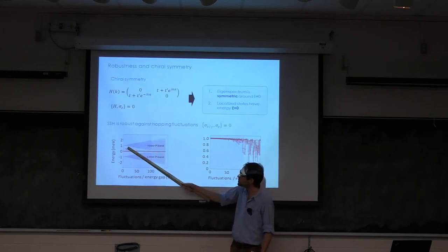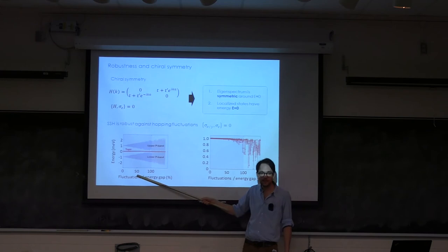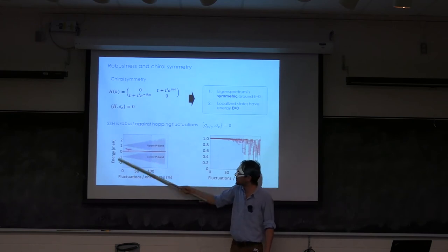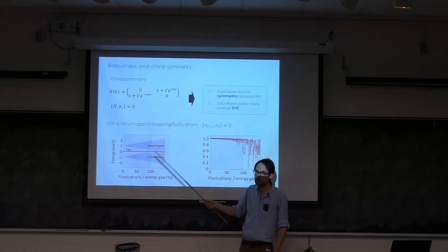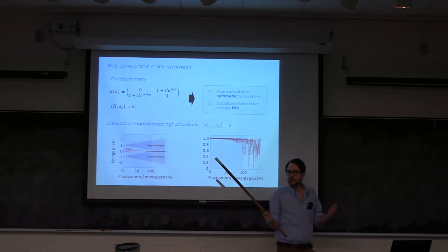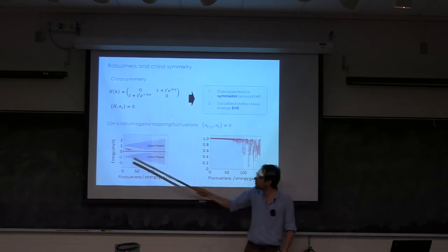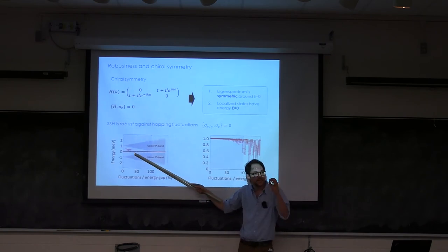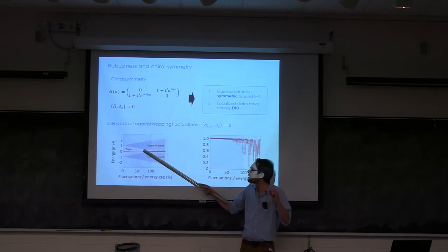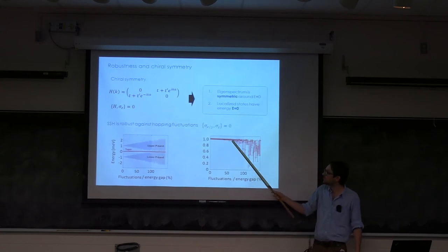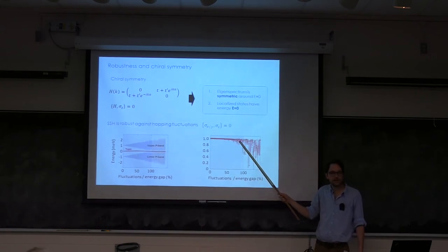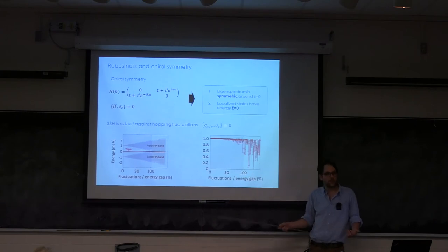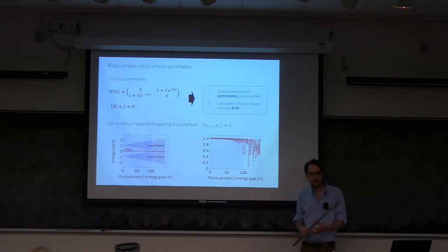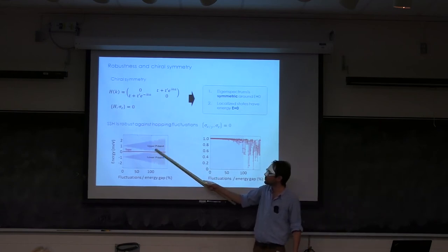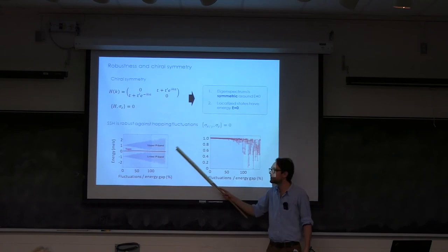And this is a calculation that shows that if you start to introduce fluctuation in the hopping energies, you see here this is the band spectrum. Your two bands become broader and broader because your hopping energies are less and less defined. But your edge state always stays mathematically exactly at the center of the gap. And it's highly, highly localized on the first pillar at the edge of the lattice. Unless the perturbation becomes comparable to the energy gap, which is the energy scale that protects you. You're not protected against anything. At some point, your edge state will start to hybridize with the modes of the bands and start to delocalize.